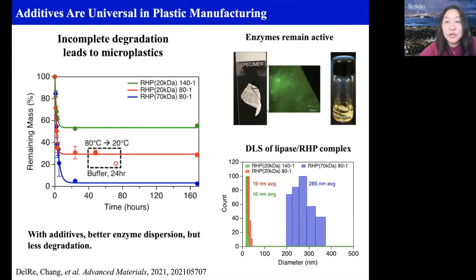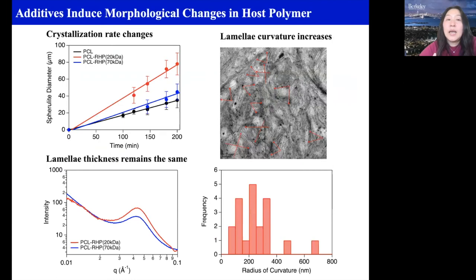So let us go back to see what happened. We attribute it to the additive. It turned out we were correct, because as we add additive, our crystallization changes. The system crystallized much faster because the nucleation of the crystallization changes. But we are not changing the lamellar structure. So at the monomer level, how the system is going to pack, as well as at the lamellae thickness, how the polymer chain is going to fold back and forth to form the lamellar structure, is not changing. The only thing we change is the curvature. So this is where we go back and look at the image analysis, at the curvature. So what does the curvature change?